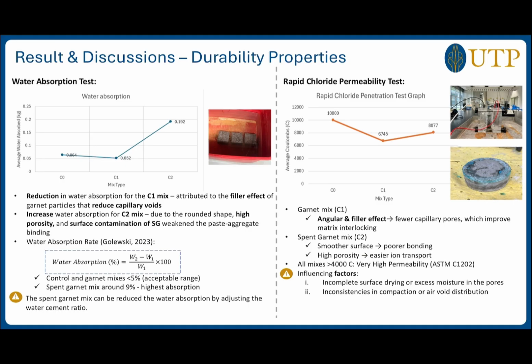And this is the formula that I used to calculate the water absorption rate. And I got control and garnet mix below 5%, which is within the acceptable range. And for the spent garnet mix, it's around 9%, which is considered high absorption. And based on Golewski in 2023, a result under 5% is considered high quality and dense concrete. Next is the rapid chloride permeability test.